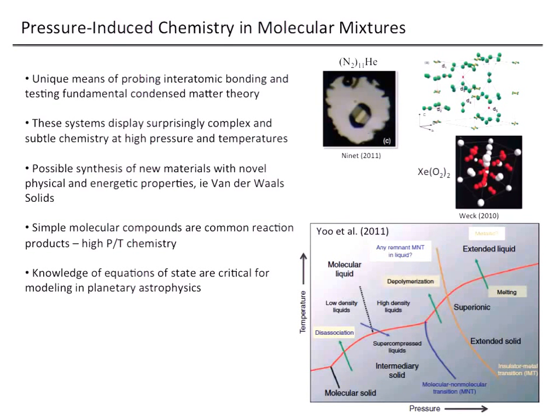This is interesting because at high pressure you can actually form whole new compounds called van der Waals compounds, where you have molecules essentially assuming a solid crystalline structure and interacting very weakly with each other. So they're still in molecular form. In this case, nitrogen is still triple bonded, but you can actually form a lattice compound of nitrogen and helium. So this is a crystal of nitrogen and helium together. The same is true for xenon and oxygen, for instance. And xenon, being a noble gas, is not something you think of easily being able to bond with other things.